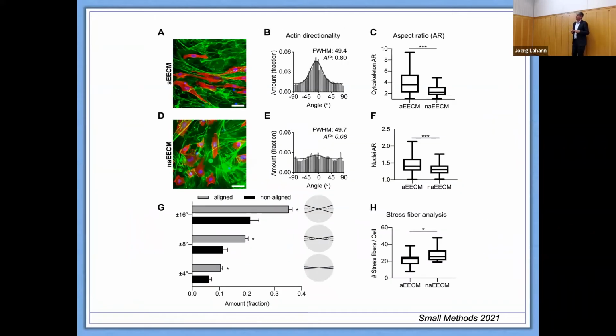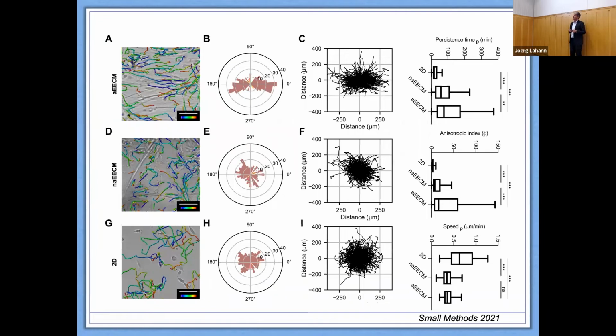In fact, it's relevant for cells as well, because that then induces cell organization. We're using this right now mostly in the context of cardiomyocytes, and a little bit with cancer cells as well. So there is a little vignette here where we can control the organization of the fibrils themselves through the shear field. And we think there's maybe an effect here, so we're looking at proliferation and the different distributions in those cells. There seems to be an effect on the cells as well. These are fibroblasts, obviously, but as I said, we're also looking at cardiomyocytes now, and cancer cells a little bit. In this case, it's not so much the anisotropy that is changing, it's the velocity. The velocity in the direction is the factor that is most influenced by the ECM here.